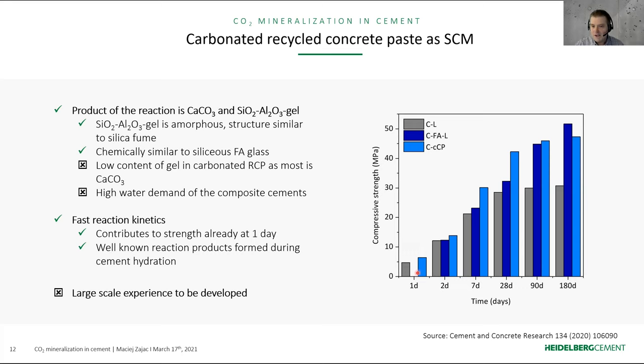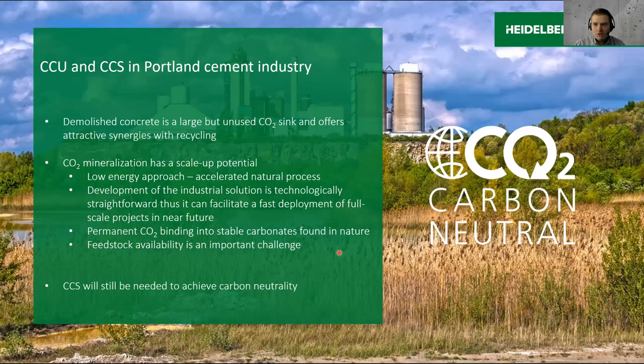And you see the evolution, and you see here clearly the contribution of the pozzolanic reaction of the alumina silica gel on the compressive strength, and a very nice increase of the compressive strength already at 1, 2, and 7 days. However, at 90 days, as you see, the fly ash is catching up, it is reacting slowly, and then we have a similar compressive strength. So overall, I show you one of the carbon capture and utilization technologies that we are developing.